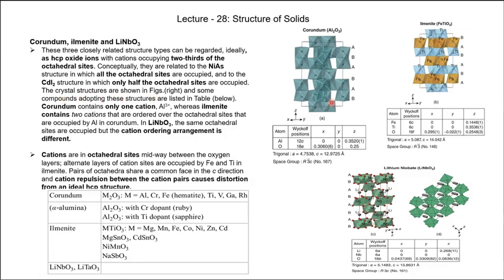The crystal structure is shown here. If we take the crystallographic 3-dimensional arrangement of this structure, we can describe the unit cell as trigonal, and the space group is R3c. And the number of the space group is 167. So if it is trigonal, the cell parameter is there. A is equal to this, and C is equal to this Angstrom. And we can also say about the Wyckoff positions of these atoms, aluminium and oxide. Wyckoff position 12c for aluminium, and for oxygen, it is 18e.